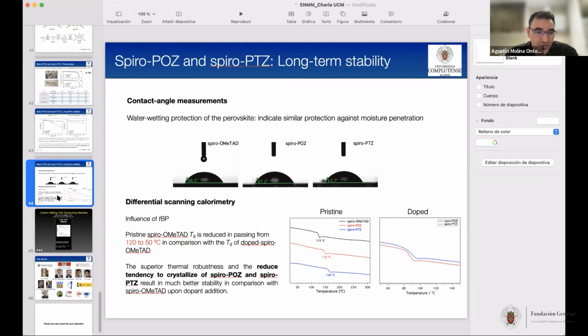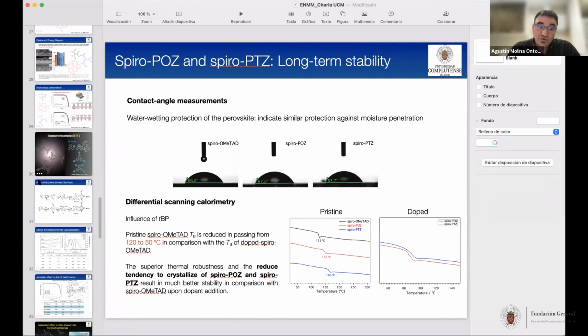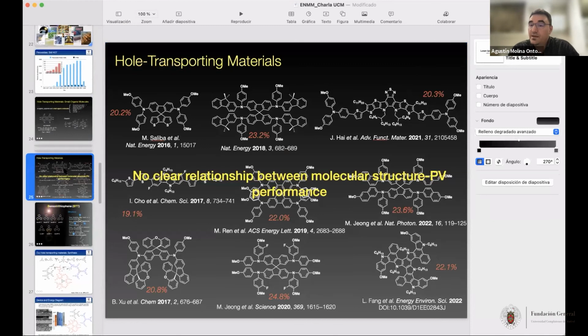Well, that's a good question. Introducing more triphenylamines or donor molecules will not necessarily affect the efficiency. Even with just two TPAs, you can obtain very nice efficiencies. The nature of the core may also have some influence. If you can control the pi-pi stacking of the molecule, you can enhance the conductivity. But on the other hand, when you have Spiro compounds, that is completely different.